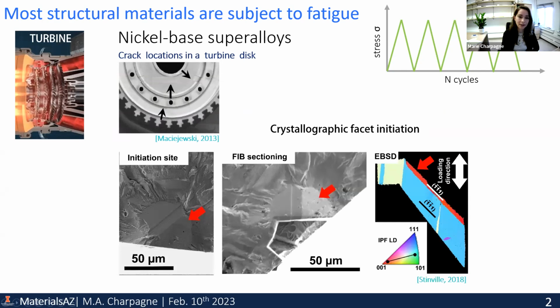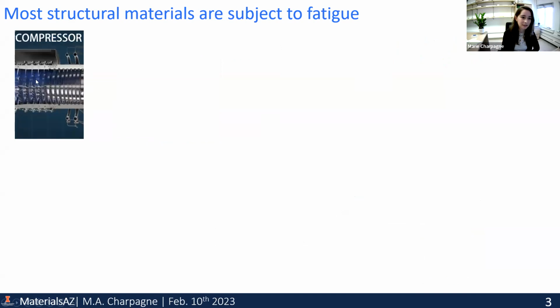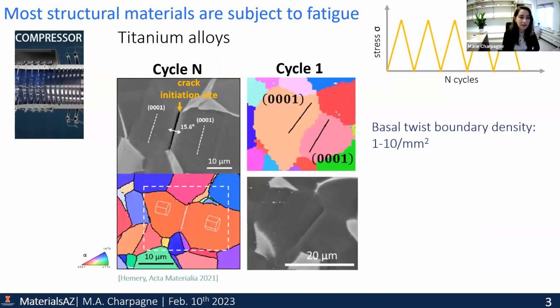And so when we do so, we identify our cracks and look at these initiation sites for fatigue cracks by looking in the SEM, scanning electron microscope. We oftentimes see some crystallographic facets that show up, meaning that there is most likely a linkage between the microstructure and where those facets are in the material's structure at the small scale, and where the early fatigue cracks are going to form. So that's the first hint that fatigue is actually related to the material's microstructure, so the crystalline structure of the materials. And looking at the cooler parts in this gas turbine engine, we have titanium alloys.